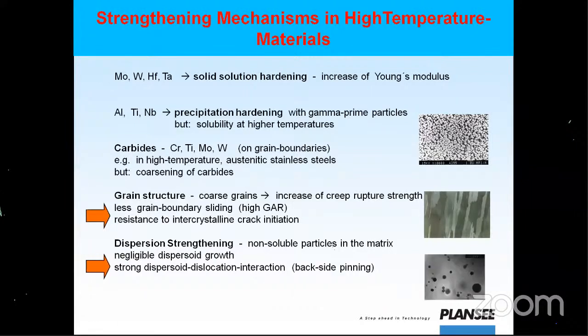Then the third thing is dispersed strengthening. That is the one area where we have a lot of PM2000. This material shows capability up to 1200 to 1250 degrees centigrade without any oxidation issues. This is very good. The only thing is that forming, welding, and joining are very difficult. But it's been used.